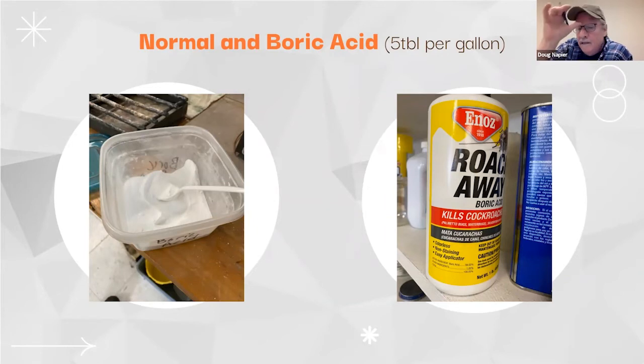If a piece doesn't have detail, or if it doesn't have a bunch of thin areas that have a tendency of breaking off, I just use the straight Satin Cast or Ultravest without any additives, and I get a good result. But on those pieces that are fragile, that do have a tendency of breaking out, I'll take about 5 tablespoons of powdered boric acid per gallon of water. So I'll get a gallon of water, usually hot water, and I'll put 5 tablespoons of this powdered boric acid in it, mix it up, and then let it sit aside. And when it cools down to room temperature, that's when I can use it.